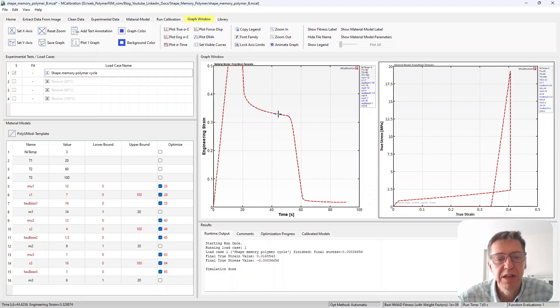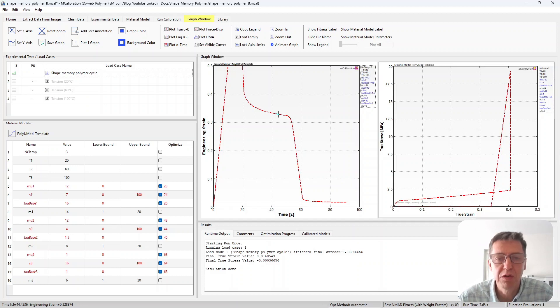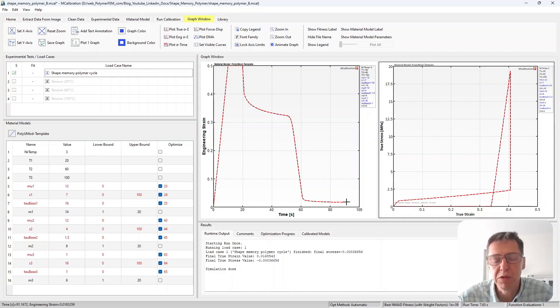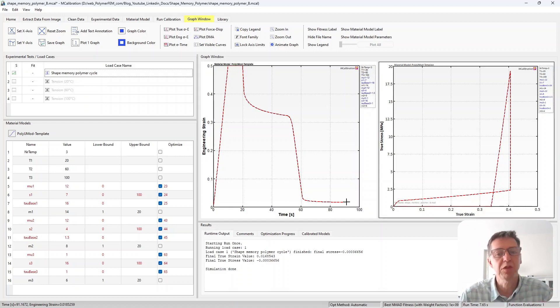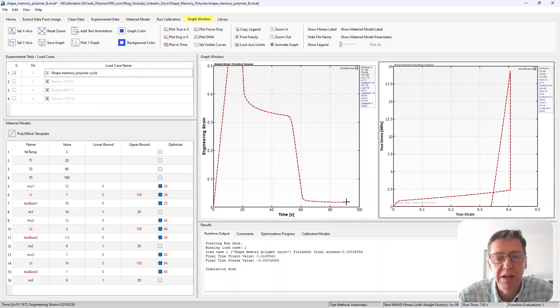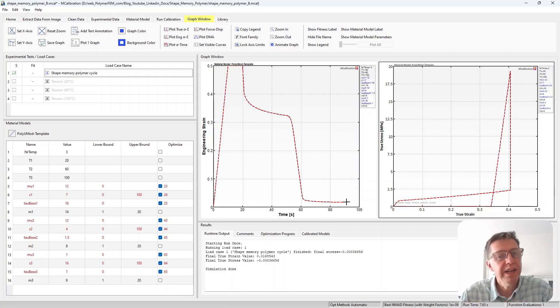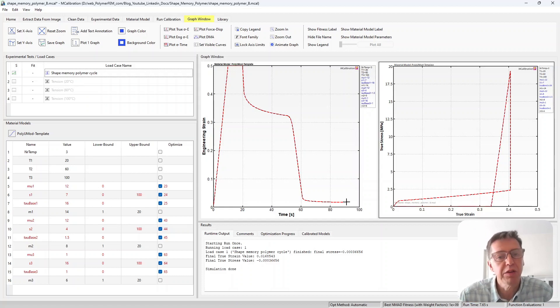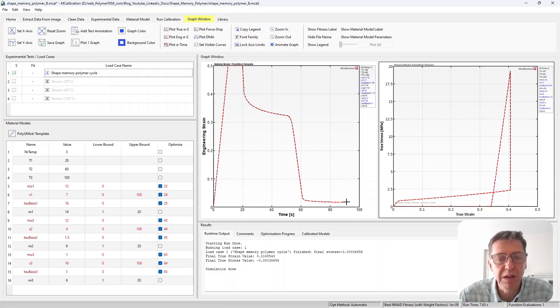We'll see in this case we have after the deformation followed by unloading and cool down, we have a much higher residual strain in the specimen, about 35% strain left. And then we apply 50% and we have a very substantial recovery of that. So it's a very substantial shape memory effect for this particular material. Of course I didn't show you experimental data here. A lot of the science goes into creating these materials to have a lot of shape memory behavior in real life.